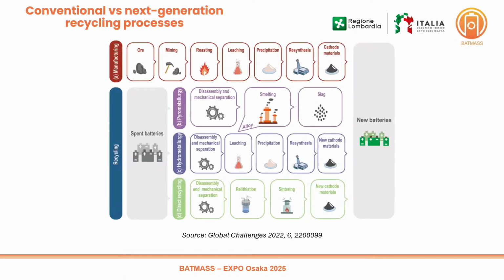But of course, when we talk about recycling processes, we have essentially two main actors and one new possible way. The traditional way for recycling critical raw materials is the metallurgical approach. Essentially, we have two choices. The first one is the pyrometallurgical approach. It's the most simple. We need only an oven able to reach 1,000 to 1,200 degrees, able to melt all the battery, and from the melt it's possible to obtain an alloy where we can find critical raw materials like cobalt, nickel, and iron, and after a leaching process it's possible to obtain these elements.